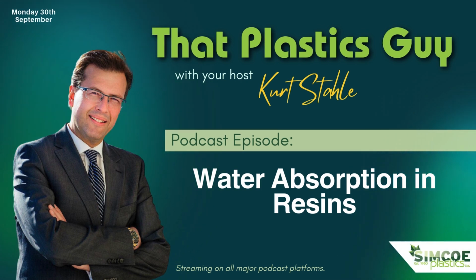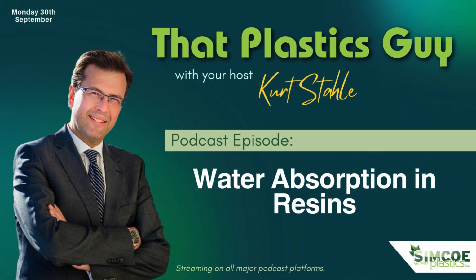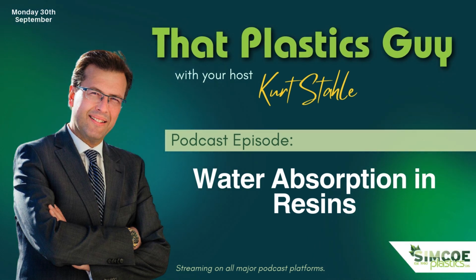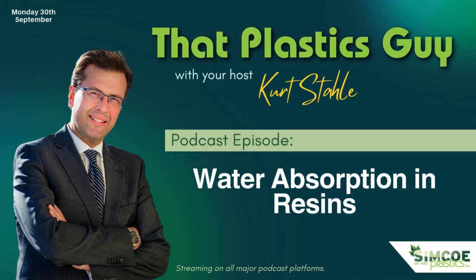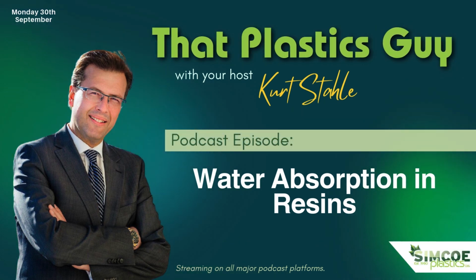One last one. Cross-linked polyethylene, typically used for rotational molded kayaks, canoes, that type of thing. Very, very durable material. The dry moisture content, 0.005%, and it maxes at 0.01%. Again, just showing you it's a resin that is not affected by moisture content. And obviously, if you're making a boat out of it, you don't want it to be impacted by water.